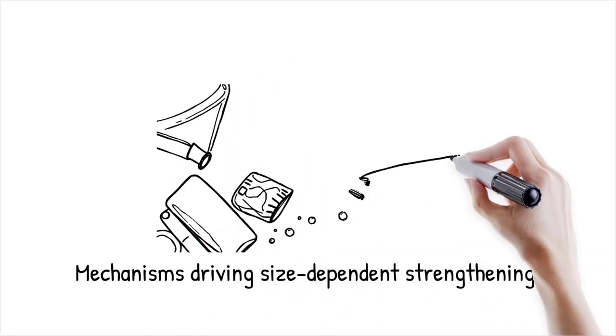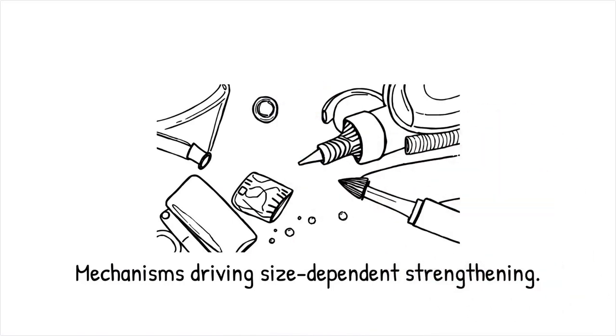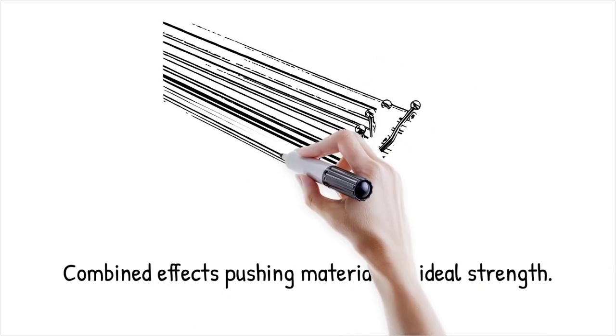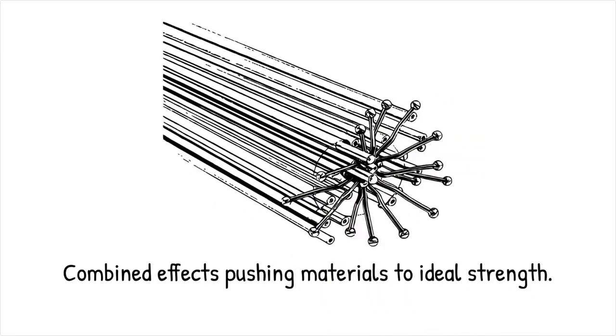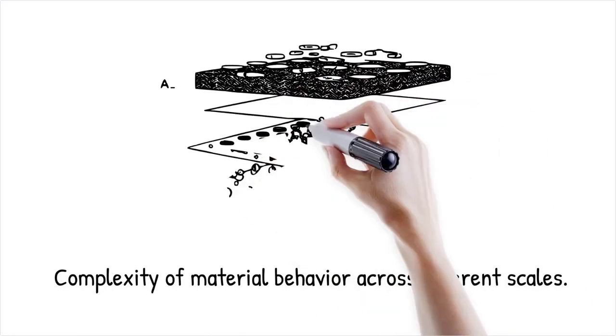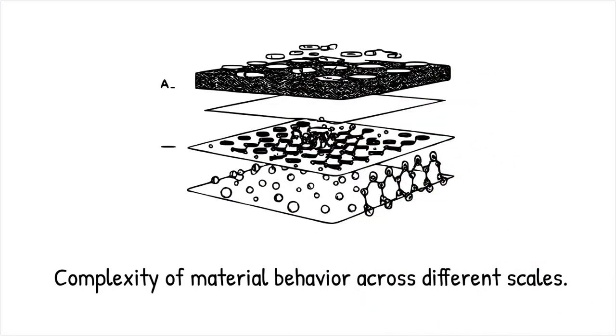The enhancement in strength at the nanoscale arises from mechanisms such as dislocation starvation, surface-dominated mechanics, constrained plasticity, and limited defect nucleation. In extremely small volumes, dislocations cannot multiply or propagate easily, resulting in what is known as dislocation exhaustion or source-limited deformation, and the increased surface-to-volume ratio amplifies the influence of surface energy, pushing the material closer to its ideal strength. Metallic glass nanowires, for example, can exhibit high tensile strengths because their deformation occurs through shear banding without the usual dislocation mechanisms to relieve stress, similar to a pristine crystal without cracks, where pressure builds relentlessly, making the material appear unnaturally strong. This paradox also highlights the complexity of materials' behavior across different scales, underscoring the breakdown of continuum assumptions at the nanoscale where new rules of behavior emerge.